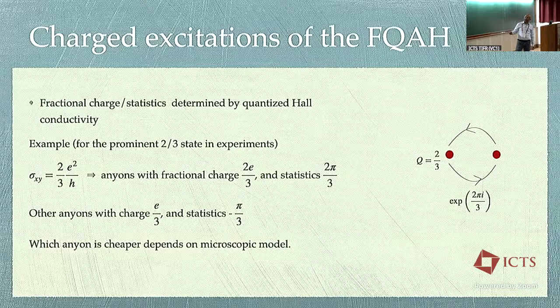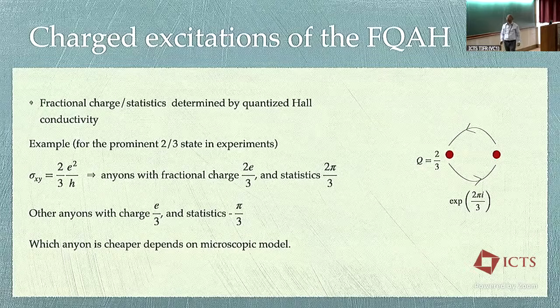For this 2/3 state, the Hall conductivity of 2/3 e squared over h implies that there are anyons with fractional charge 2e over 3 and with fractional statistics of 2 pi over 3. And a simple argument also tells you that you must also have other anyons with charge e over 3 and with statistics minus pi over 3. Which anyon is cheaper depends on the microscopic model. It depends on detailed calculations. But these anyons are all available to the system as a matter of principle.